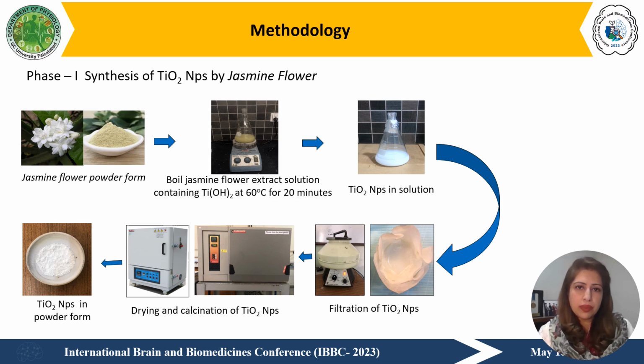Now, let's talk about the methodology for the synthesis of the titanium oxide nanoparticles by the jasmine flower in the phase 1. First of all, the jasmine flower was dried and then they were crushed in a powder form. Then 80 ml of the jasmine flower extract solution and 20 ml of the titanyl hydroxide were mixed together. This solution was heated at about 60 degrees centigrade for 20 minutes until white milky deposit of nanoparticles were formed. This milky white solution containing deposits of titanium oxide nanoparticles were kept in shaking incubator at about 28 degrees centigrade for the next 24 hours.